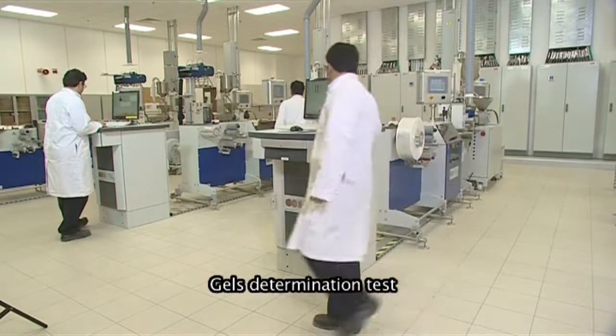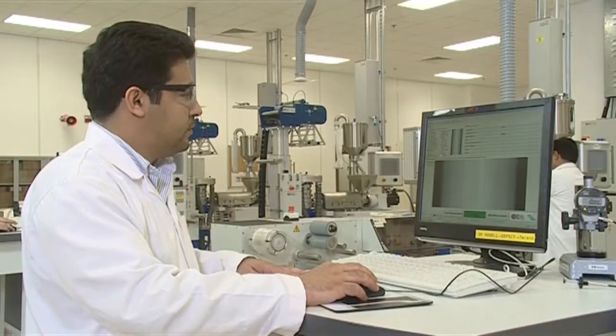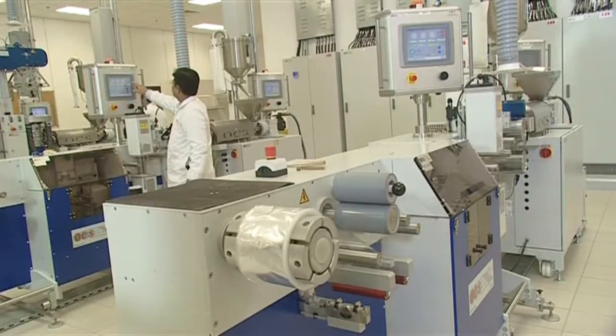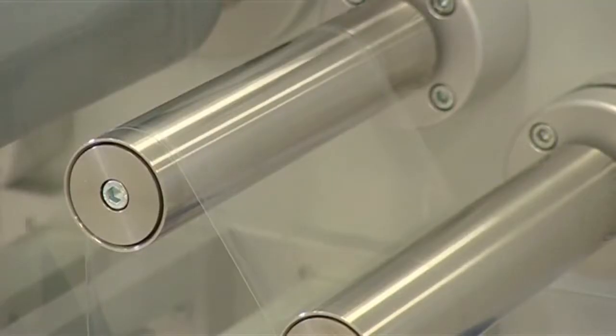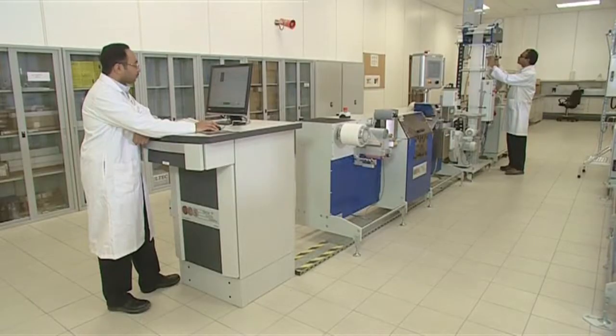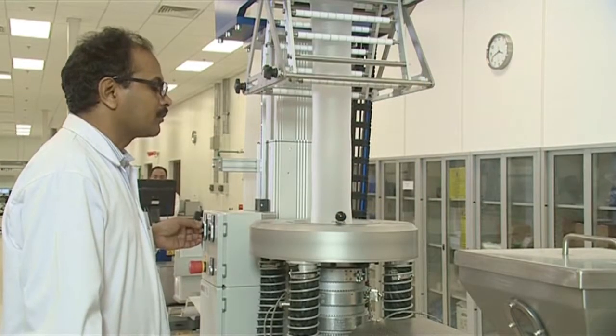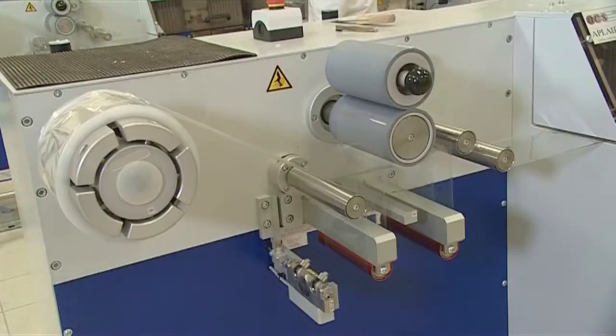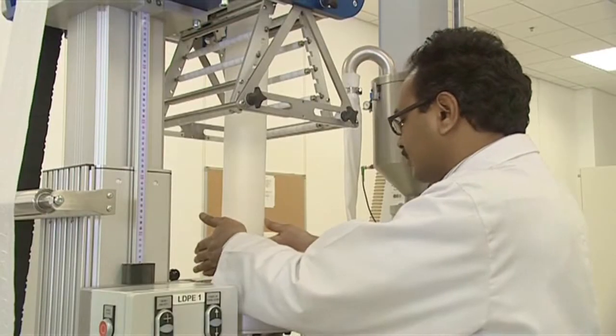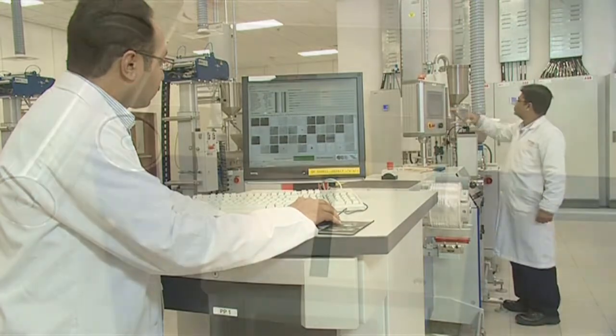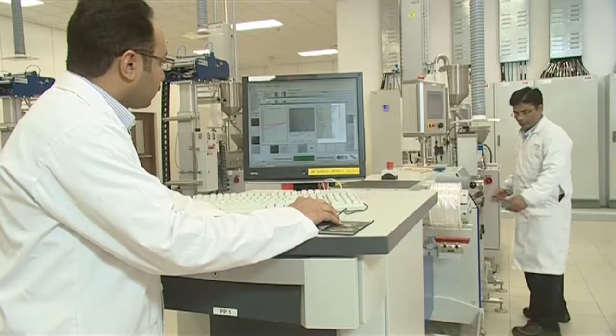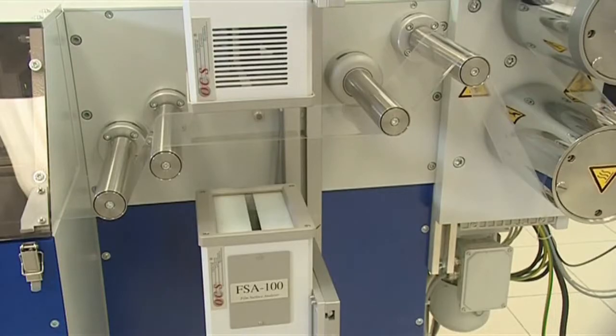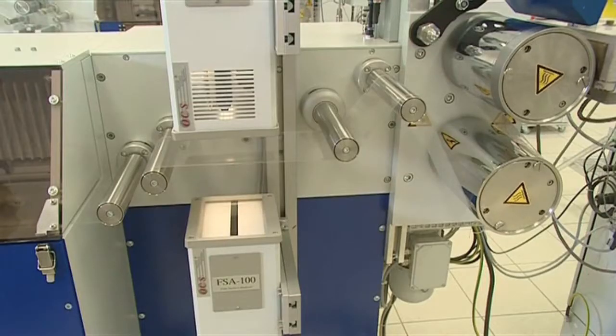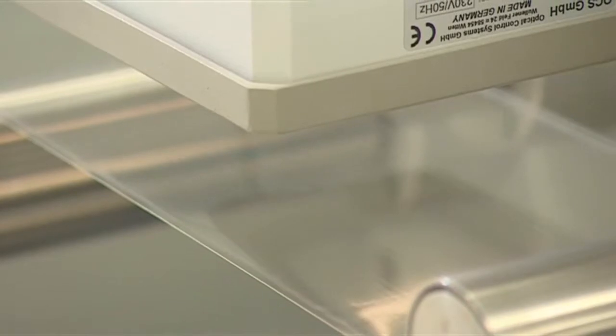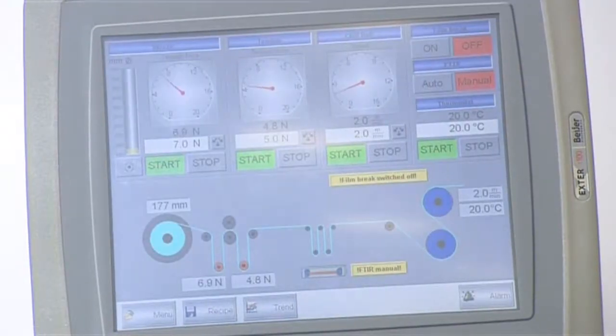The gel determination test for film, pipe, and fiber grade products is very important. To perform this test, Saudi Kayan has selected OCS film extruders. Cast film extruders for PP, HDPE, and blown film, especially for LDPE. The gels are detected by passing a film over a high-resolution camera, which takes the picture of the gels. Gel size and shape are recorded and measured with the help of a computer.